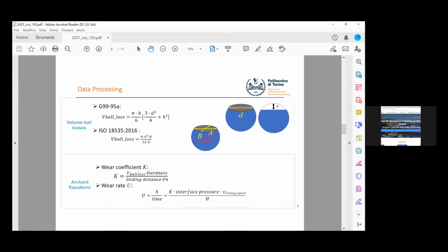For each pin-on-disc test, wear of contact body was calculated by appropriate linear dimension, length or shape change of the pin, and depth or shape change of the disc track. Subsequently, wear linear measurements were converted in wear volume through appropriate geometric relations reported in the two standards G99 and ISO 18535. A further parameter quantifying wear is introduced by the Archard equation. This approach is adopted to model the friction phenomenon for the purpose of determining the wear coefficient K, a dimensionless number, and the wear rate U expressed as micrometer per hour.